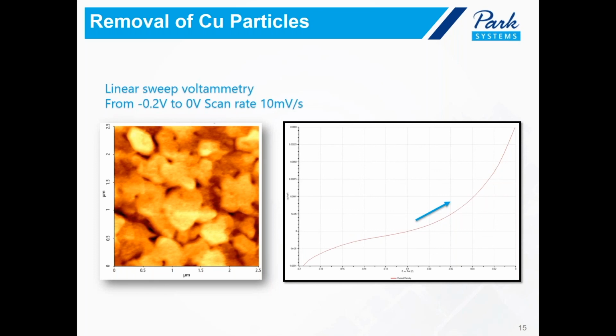Then finally, we run the fourth and last test with the same condition. This time, we got an AFM image of the gold surface which is essentially clean and free from copper particles. And now we can clearly observe the crystal terraces of the gold surface.